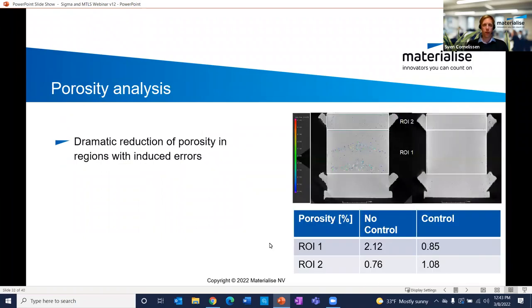Of course, we've looked a little bit closer and did a porosity analysis using the CT software. Now, please don't look at the absolute numbers of these porosity values, because we didn't calibrate the pore counting routine in the CT software. So in absolute numbers, they are meaningless. But since we are using the same algorithm everywhere, relatively, we can, of course, compare these numbers. And so, lower is better, right?